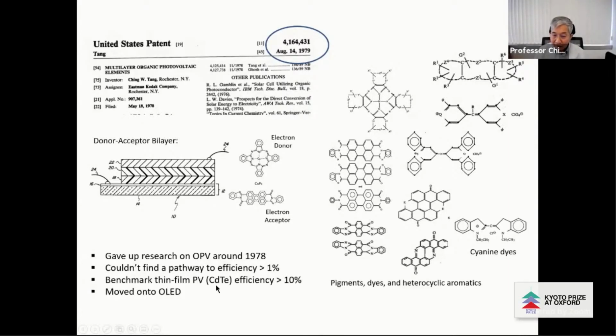And the benchmark thin film PV, for instance, the cadmium telluride that other people in my lab at the time were working on, their benchmark efficiency is 10%, and they achieved more than 10%. So for me to keep working on a very poor device was just very discouraging at the time. So I moved on. And in this patent, I basically summarize a lot of the materials that I used for both donor and acceptors. This turned out to be quite useful even later on in research in the field. So I quit in 1978, no longer working on organic solar cells.